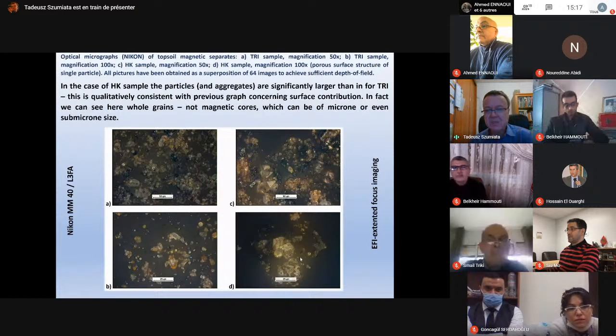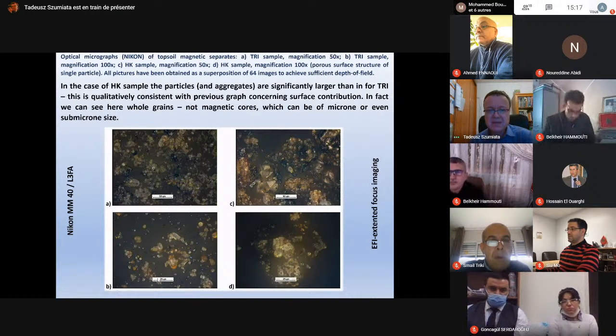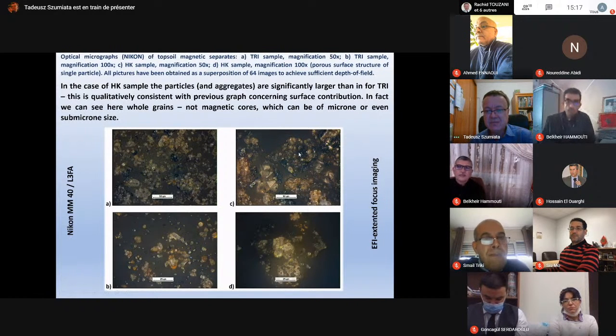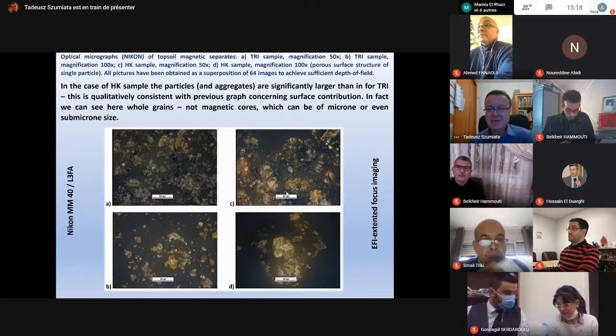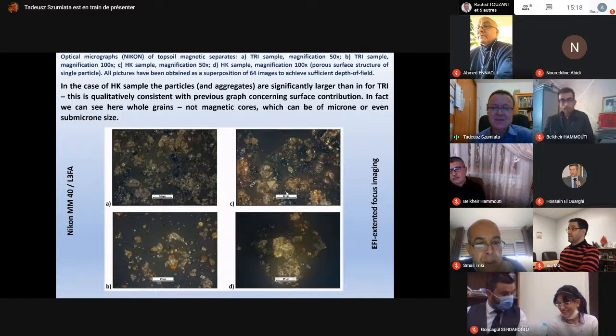The presence of this contribution could be somehow related to the size of the grains. Here you can see optical micrographs of the samples with the huge contribution of this surface component, and here these grains are smaller than in the case of the sample with a small amount of surface magnetite component. In fact, here you can see some big conglomerates of grains. This scale is 50 micrometers, but we expected that the magnetic cores of magnetite are of order, for example, 100 nanometers. So we cannot see them, but somehow the total size of grains is proportional to the size of magnetic core in these samples.